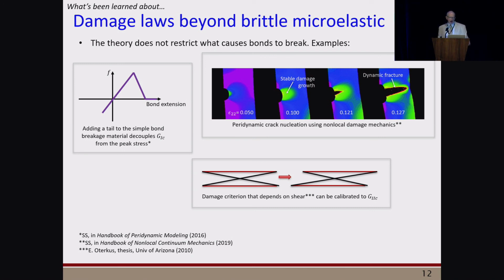So what have we learned about damage laws in peridynamics? I already talked about the simplest brittle microelastic material model. One problem with that model is that for a given value of horizon, the peak load, which is determined by the maximum in this bond force curve, depends on the predicted value of G1C, the critical energy release rate.